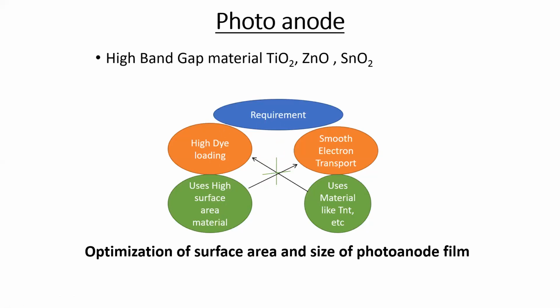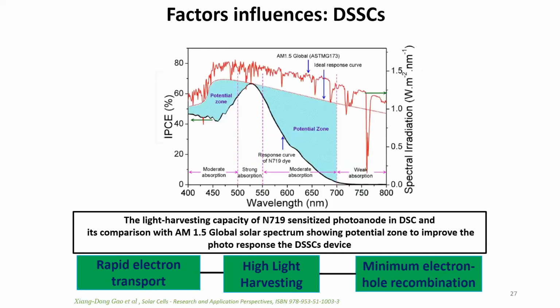So in DSSC, up to now, the reported efficiency is approximately 14 to 15%. Now in my research, suppose this is the N719 dye, the red color dye that I showed. This is the absorption spectrum of that dye molecule. Here we see that the light absorbs very highly at 500 to 550 nanometers. Absorption is very good, but after 550 the absorption starts reducing, and before 500 nanometers the absorption is not that good. So if I can increase the light absorption in this particular zone, maybe I can get good efficiency. I consider this a potential zone, where if I can play around with the plasmonic nanomaterial that I discussed, and this area absorbs more light, I can have really good light harvesting and manage to get better efficiency.